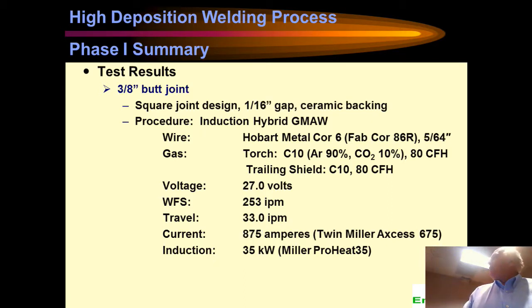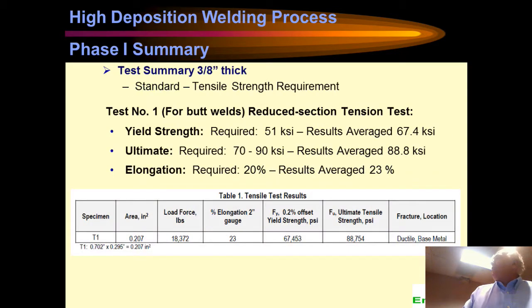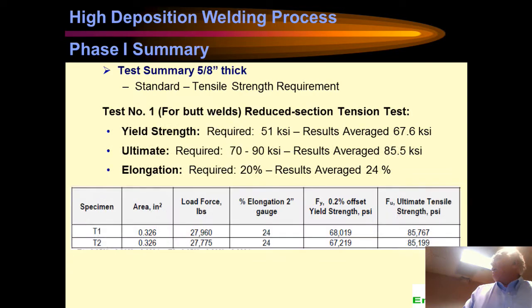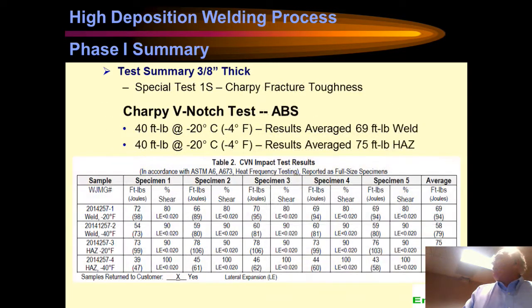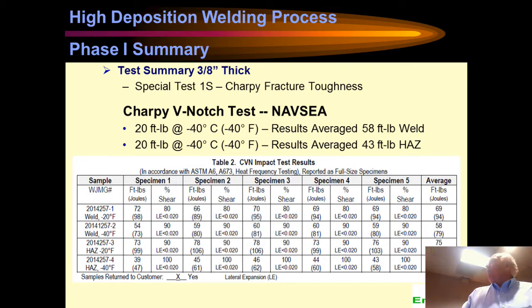On the 3/8 inch material, we were running a little slower. This was one of the earlier ones we did, so we were running a little slower, both on wire feed speed and travel, obviously. And I just stuck these in. I won't spend a lot of time on them, but there's tensile testing for both the 5/8 and the 3/8 material. These are Charpy tests that we did, and we did both the ones that would meet the American Bureau of Shipping, which is very similar to the AWS D1.1 code, and then we also did the Naval Sea Systems.